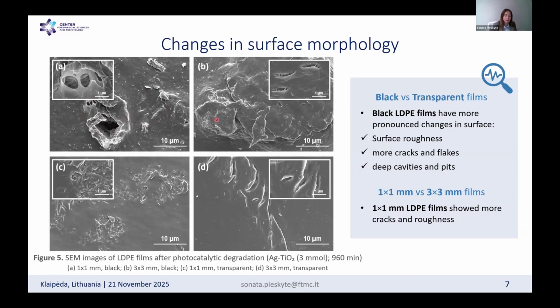So these highly pronounced surface changes are seen in both the films with a size of 1 by 1 millimeter and 3 by 3 millimeters in the case of black films. And parts C and D of the figure represent transparent LDPE films. Here we can see that of course there are some changes, because these results are after 16 hours of UV radiation together with a catalyst. But the changes and the effect on the surface of transparent LDPE films are not that well pronounced, and we can see that they take place only on the top layers of our LDPE films, which means that there is no substantial internal damage or defects in the deeper inner layers of the transparent LDPE films.